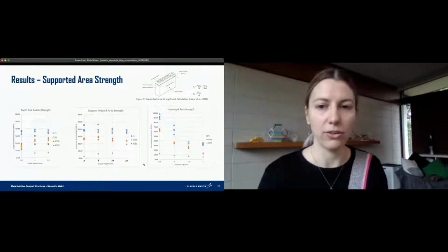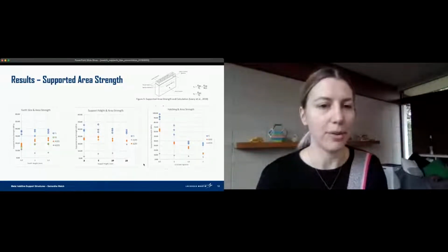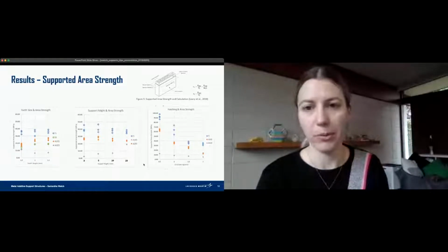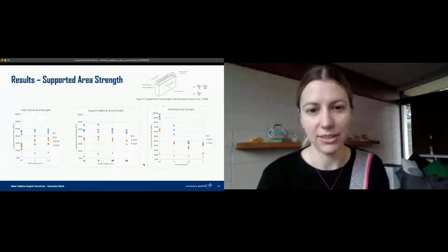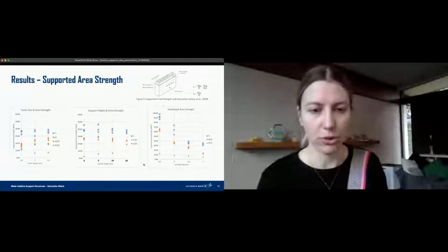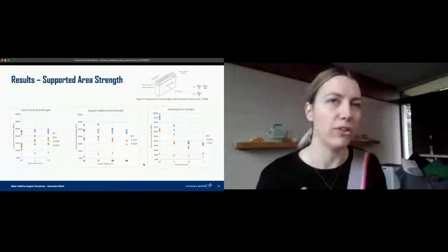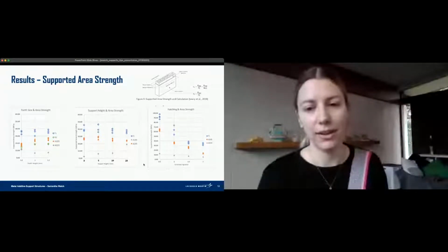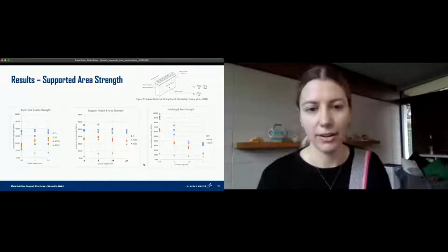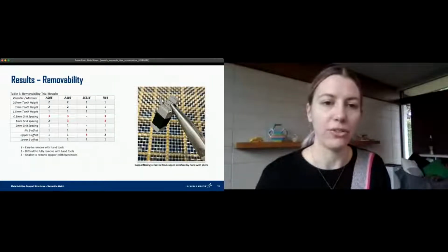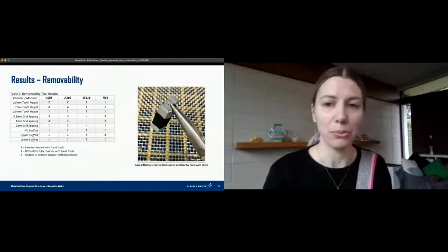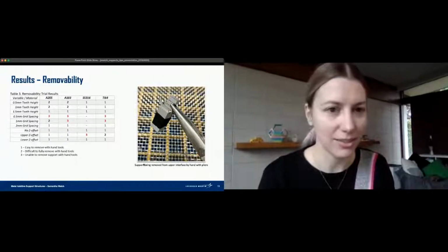As we moved that grid spacing tighter, it trapped a lot more powder. It was no longer able to be removed with hand tools. And so if you're in need of a stronger support structure, I would really recommend using more of a hybrid approach of a sparse grid and then some solid posts or thin walls rather than densifying all of your supports and making it a nightmare to post-process.